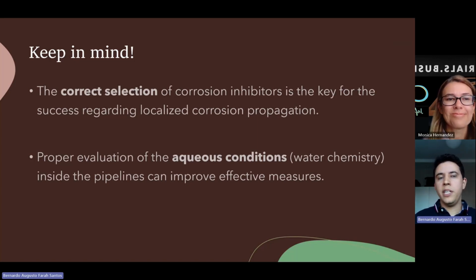Some are retarding the anodic reaction, others are retarding the cathodic reaction, others are retarding both reactions, mixed, to different extents or to the same extent. So that's very important, because that plays a significant role on the potential of your sample. So for instance, if you consider a mixed corrosion inhibitor that retards the anodic and the cathodic reactions to the same extent, there will be a slight or no change in the OCP of your sample, of your working electrode, because the OCP tends to change when you add the inhibitor, depending on whether the anodic or the cathodic reaction is retarded more or less.